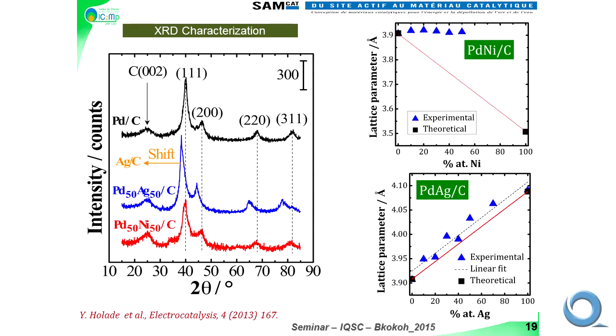It's not high. And after, if he wanted, he can add, for example, a conducting support like Vulcan carbon. And after, he dries at 40 degrees overnight, and he covers his metal. He works with 20 and 30% metal loading. At the beginning, the system is not optimized. He has an XRD characterization, for example, with silver and nickel to modify the palladium.